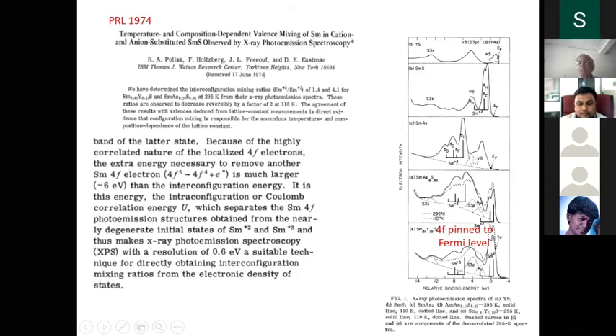Whereas I already mentioned that Mossbauer showed an average; it was lying intermediate. When it comes to electron spectroscopy, you see both the valence states. The reason is that the time scale of fluctuation is intermediate between the Mossbauer time scale, that is 10 to the minus 8 seconds, and the electron spectroscopy time scale of 10 to the minus 15 seconds. Therefore, the valence fluctuation time is intermediate between these two time scales. So in one case you are seeing the average, and in the other case you are seeing both valences.